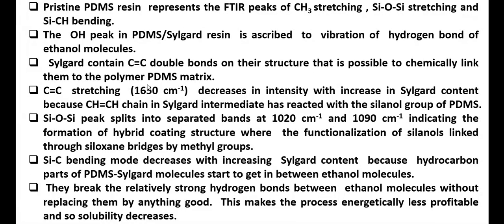So the C=C stretching at 1630 cm-1 decreases in intensity with increase in Sylgard content, because the CH=CH chain in the Sylgard intermediate has reacted with the silanol group in PDMS. The Si-O-Si splits into separated bands at 1020 cm-1 and 1090 cm-1, indicating formation of a hybrid coating structure, where the functionalization of silanols linked through siloxane bridges by methyl groups. The silicon-carbon bending mode decreases with increasing Sylgard content because hydrocarbon parts of the PDMS-Sylgard